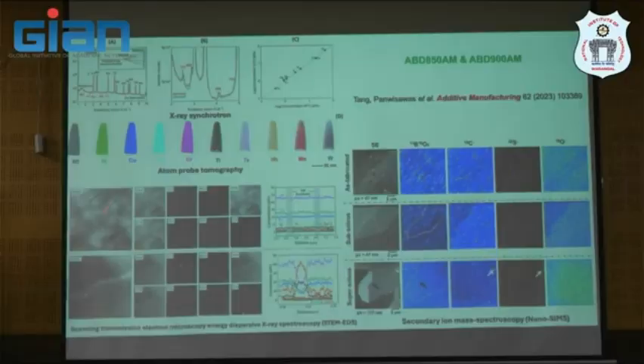combined with high resolution scanning electron microscopy or STEM. And then we do secondary ion mass spectroscopy to understand the oxide in the as-printed condition for these two alloys. And then you will see that there is no gamma prime peak detected by a high energy light source like synchrotron at all. And it's a print solid solution, actually you will see here, it is a perfect solid solution material after printing.